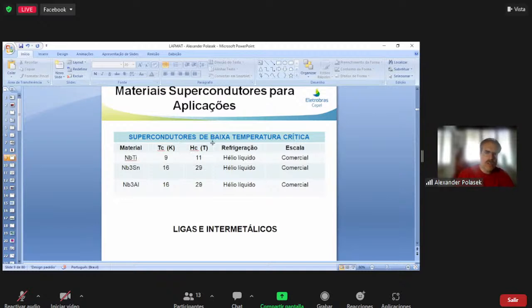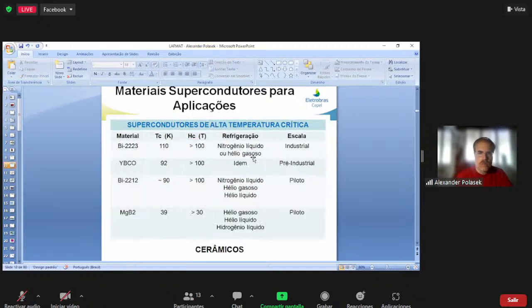And low temperature superconductors are the niobium-based ones, mainly these two, niobium titanium and niobium tin. Niobium titanium is the most commercial one, and nowadays also niobium tin, because when you need to attain higher critical fields, high fields, you need niobium tin instead of niobium titanium. All of these are fully commercial, but you need liquid helium to cool these materials.